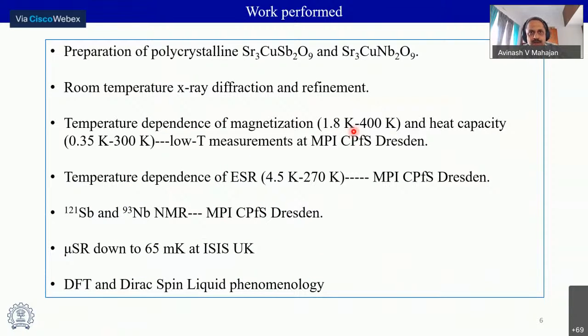I'll just go over what we have done, and what I'm going to present here is a subset of that. So we prepared polycrystalline samples of strontium copper antimony oxide, but also the niobium analog, which goes into the same structure and seems to have similar properties. There's a comprehensive series of measurements on this, supported by theory also. So there is a clear synthesis and characterization by X-ray diffraction and refinement. Also bulk probes of magnetization and heat capacity, and local probes of ESR, muSR, and NMR on these.